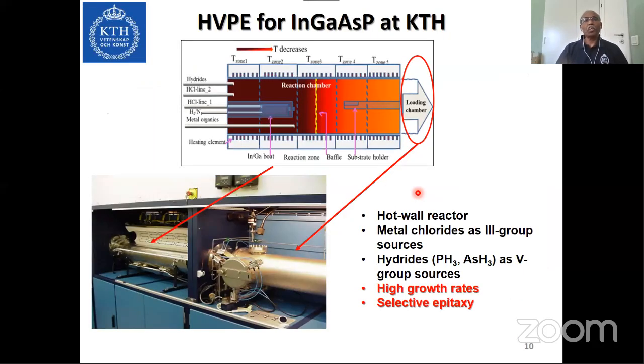Now, I am going to talk about hydride vapor phase epitaxy. It is a technique which cannot grow very thin layers, but it can grow very thick layers. So basically, it is a hot wall reactor. You see here, this is the real reactor. This is the hot wall chamber. And this is the loading chamber. From here, you are loading the wafer.